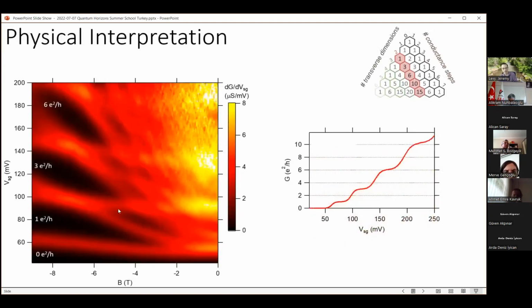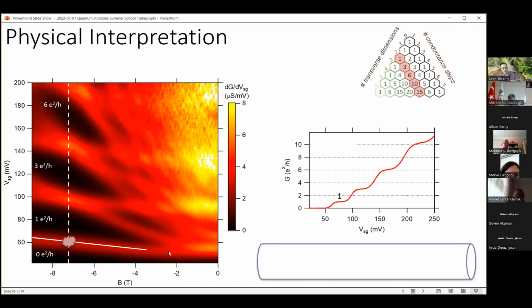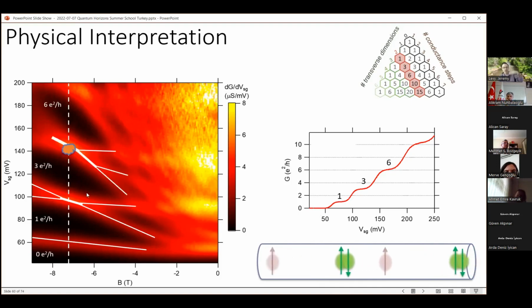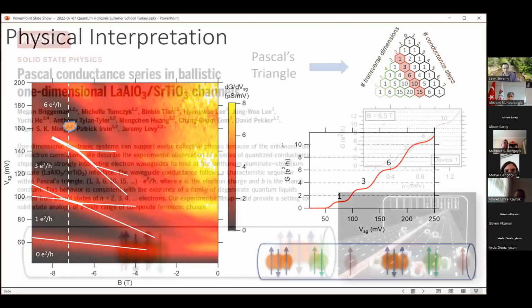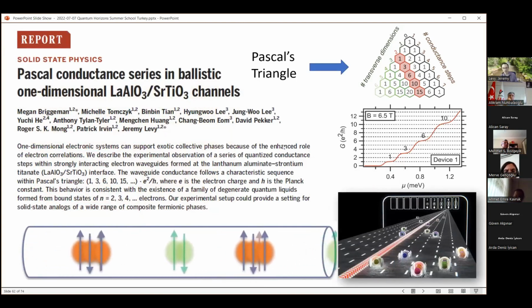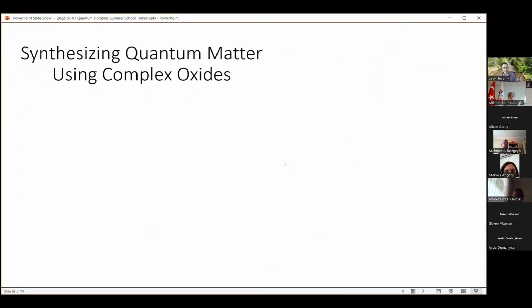And there is a sequence of them, which we interpret in the following way. So if you start with the lowest energy situation, you have 0 conduction. It's like the vacuum state. There are no electrons propagating in the system. And then as you increase the energy, you can get to a point where now there's just a single type of electron going through, spin polarized, and then you can increase more. And now, in addition to the single electrons, you have pairs of electrons, and they're propagating through. So the conduction is 1 plus 2, which is 3. And then you can continue and add the next state, which is a trion phase. And now you have 1 plus 2 plus 3, which is 6, and it actually continues. So this is a very unusual state of electronic matter that was discovered by this exploration.